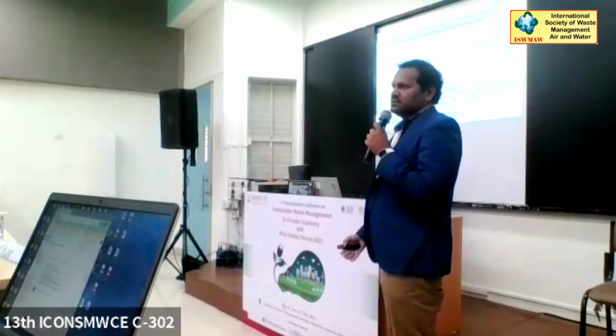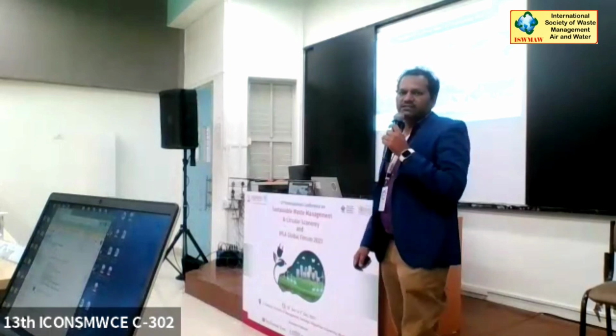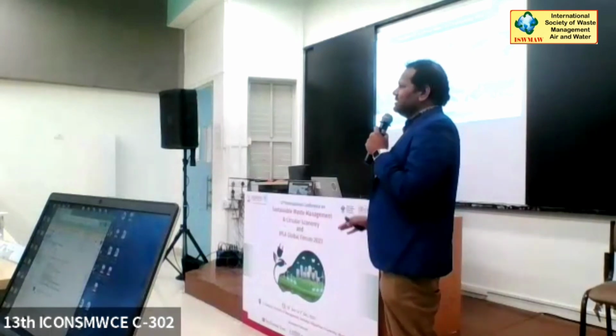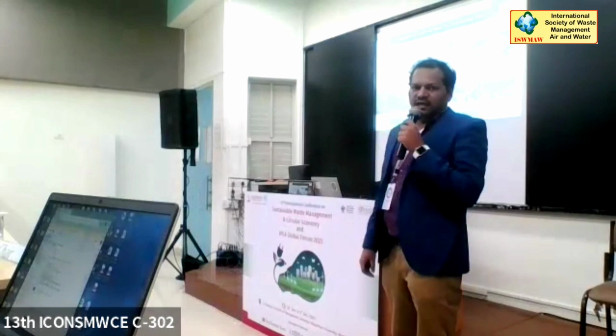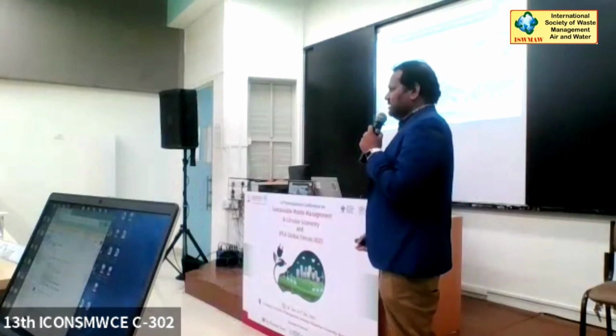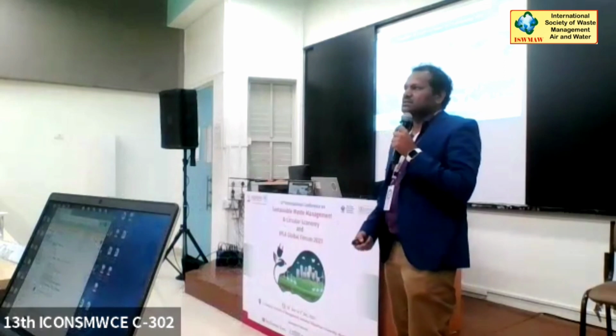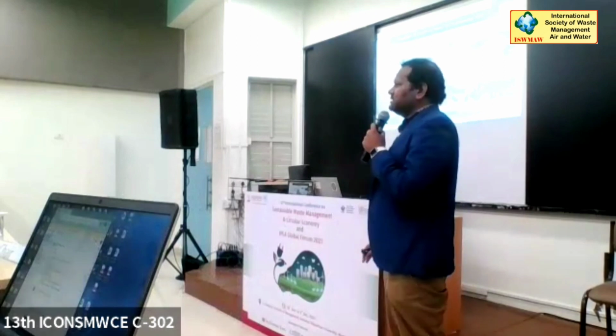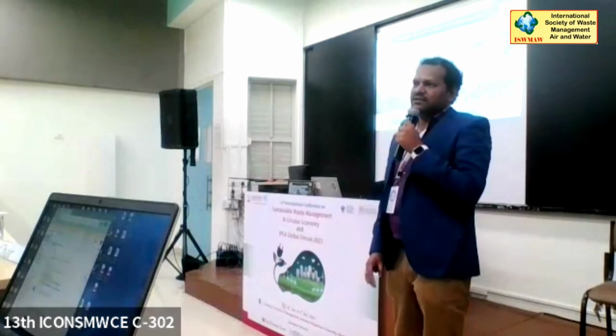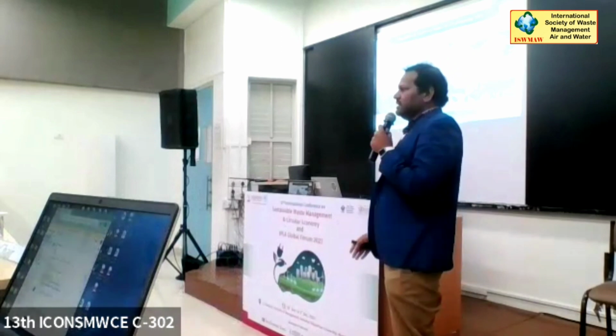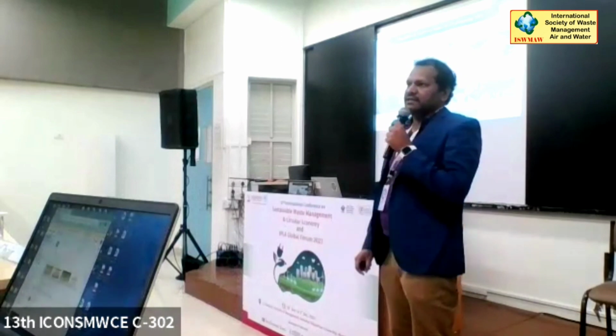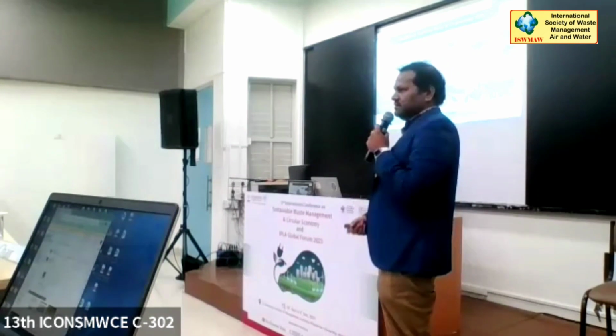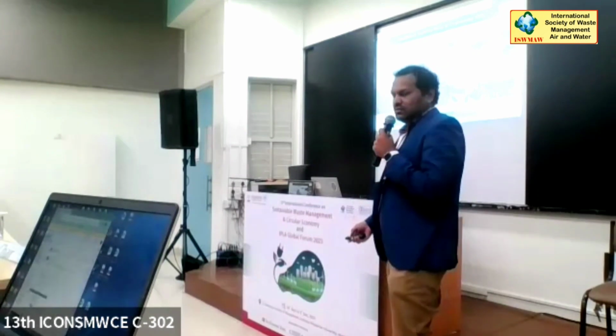Internationally, you can search for AFR utilization in white cement. The percentage ranges from 2 to 3%, but we have two lines at hand, one of 2000 TPD and one of 600 TPD, and we have reached the level of 20% TSR in one of them and around 15% in the second. And we are going further.